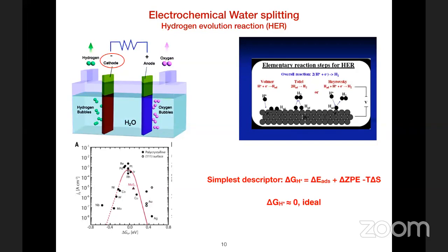So the argument is that if delta GH is far too positive, then the hydrogen doesn't like to adsorb. On the other hand, if it is large and negative, then it is very strongly bound, then it is very difficult to desorb it. So you would want to have a situation where delta GH is as close to 0 as possible. In fact, the plot on the left-hand side shows what are called typical volcano plots in catalytic reactions. So this is calculated delta GH for hydrogen adsorption on various metal surfaces versus experimental current density at some definite voltage. And as you see, the best catalysts are the noble metals, which fall around delta GH equal to 0 and show the highest current density.